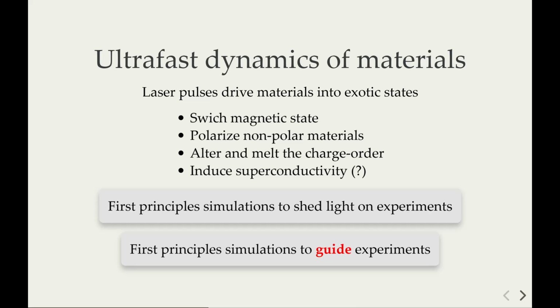This is very interesting because in the past years, experiments were capable of inducing exotic phases inside non-equilibrium states in materials. For example, they were capable of switching magnetic states in systems, inducing a polar state in non-polar materials, altering and melting the charge order, and even there are claims - now this is very debated, but there is a lot of very interesting data on this - to induce superconductive behavior in non-superconductive material dynamically. So it's a very interesting topic.